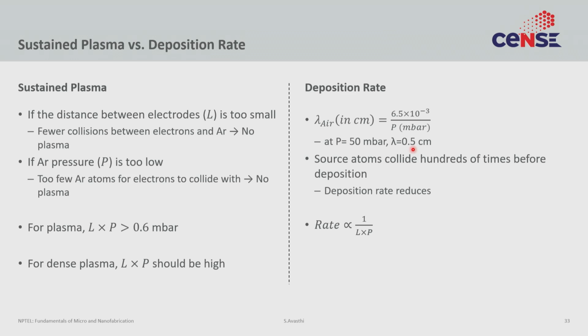However, you also want L to be as small as possible, or this P to be as small as possible. So rate is inversely proportional to the L cross P product, right? So for sustained plasma, you want L cross P product to be large. For high deposition rate, you want L cross P product to be small. These are opposing requirements, right? And that is one of the reasons why it's very hard to get reasonable deposition rates as high as in evaporation in simple sputtering systems.